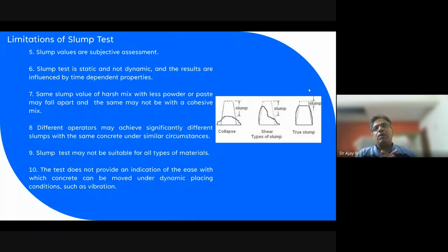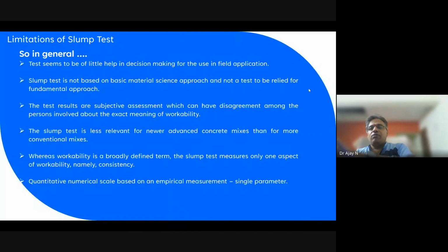But in the end result, what will happen when we attain the strength? There may be a number of factors to achieve the strength, because of the compaction, water cement ratio, finishability, placing, everything. But the fresh property is also very important for us to take care of, because the vibration effect, everything has to be taken care of when doing the concreting, but that is not indicated in the slump test. And here, sometimes we take it as a collapse. When the concrete collapses, we do not accept the concrete, and when it shears, the mix is not acceptable for placement.